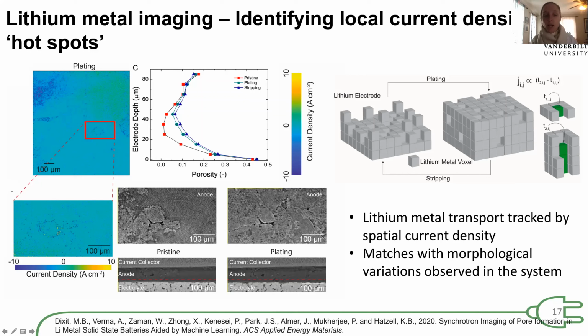And so just in a nutshell, what we're seeing across this lithium metal, which is a flat interface, is a variety of ionic flux, which means that there's the presence of directed ion transport to this lithium metal interface. As I mentioned earlier, we want to have a uniform ionic flux so we don't have any irregularities in the deposition step or the formation of irregular interfaces through irregular morphologies. What we have seen with this work is that we can track the ionic flux with spatial resolution using these X-ray images, and it gleans some insight into the impact of local ionic flux or directed ionic flux.